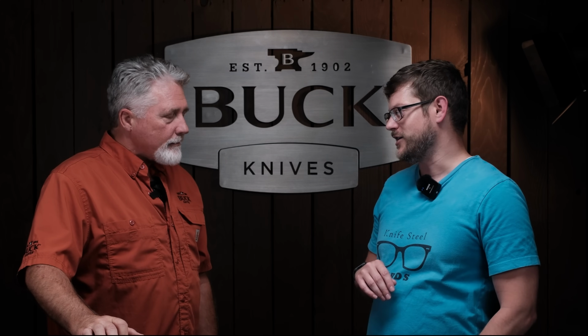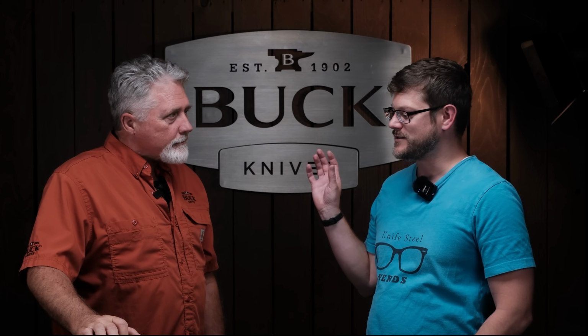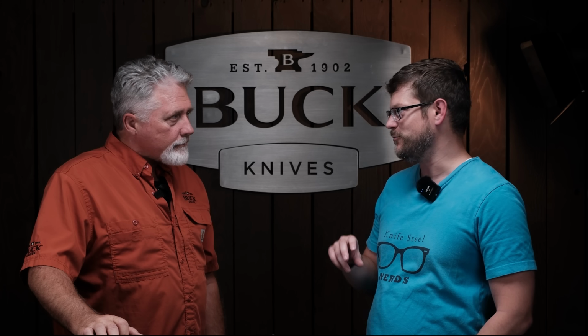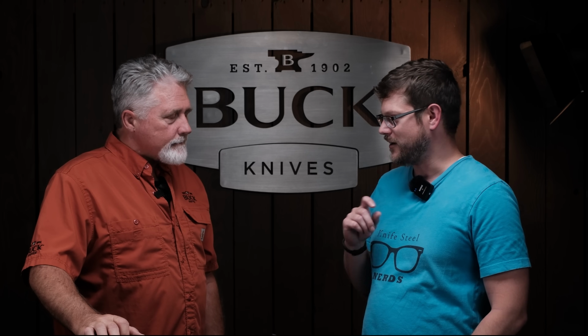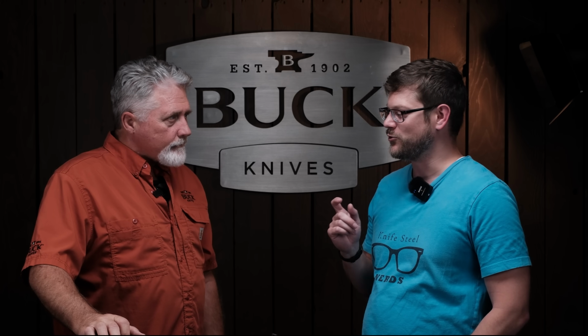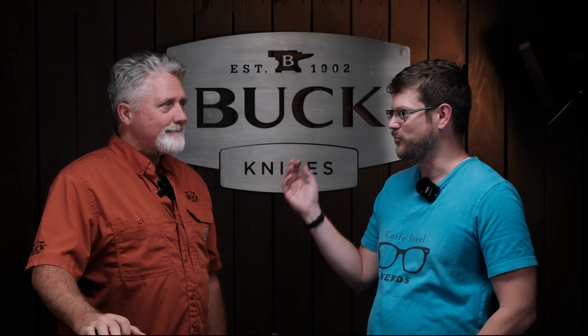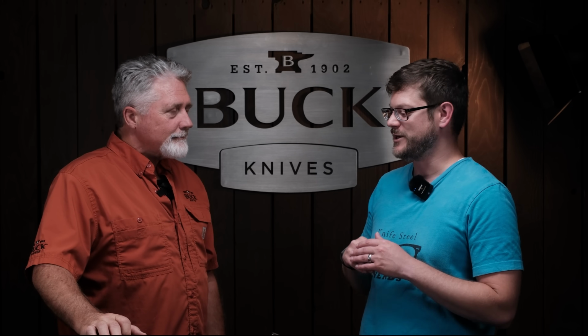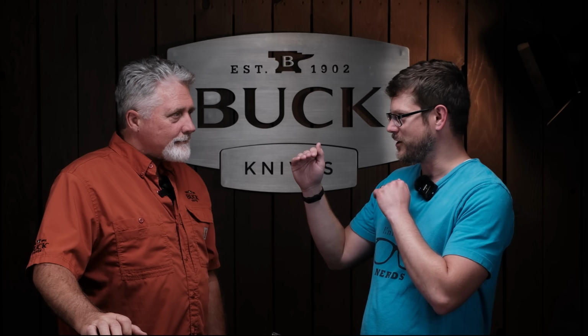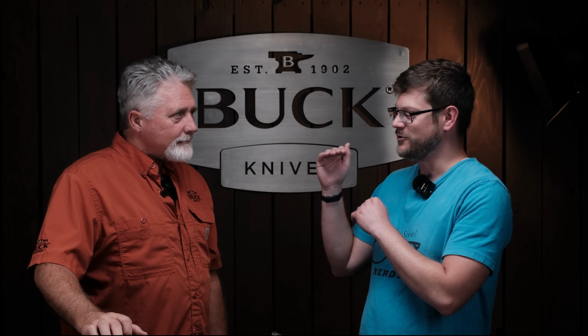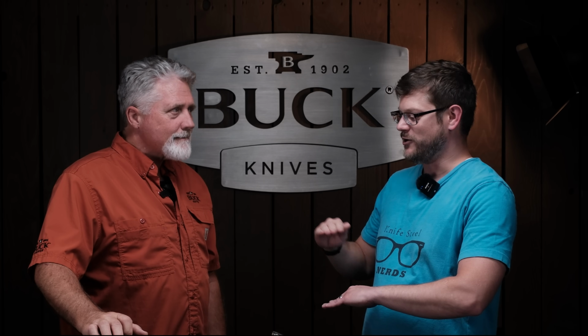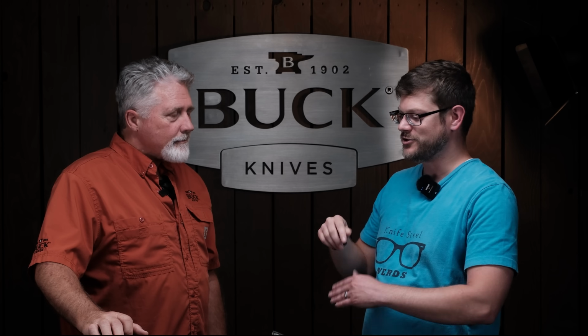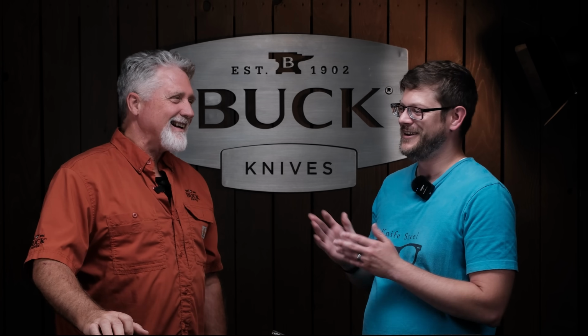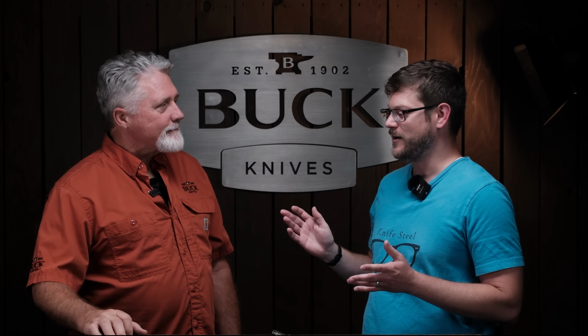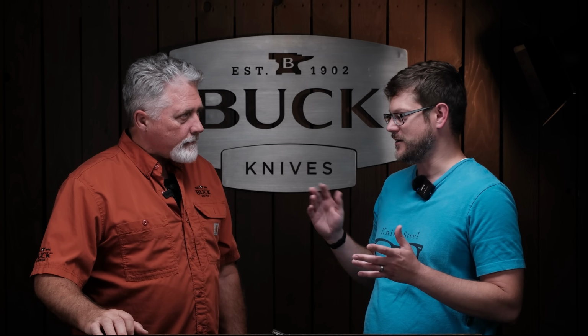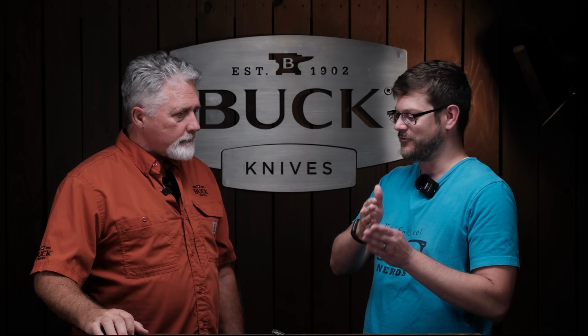So another problem that can occur in heat treating is that all of the austenite will not transform to martensite when you quench. Okay. And that is called retained austenite. And we overcome this through cryo treatments. So the cryo treatment will convert more of the austenite. So when we talk about martensite transformation, there's a temperature where it starts and a temperature where it finishes. The more carbon and chromium is in solution, the lower those transformations go. Okay. And so you have to go cryo to then get into the transformation range. So I'm trying to explain this simply. But even with cryo, you can end up with extra retained austenite, and that makes the steel softer. It will go from, so you're heating, you try different heat treatments hotter and hotter.